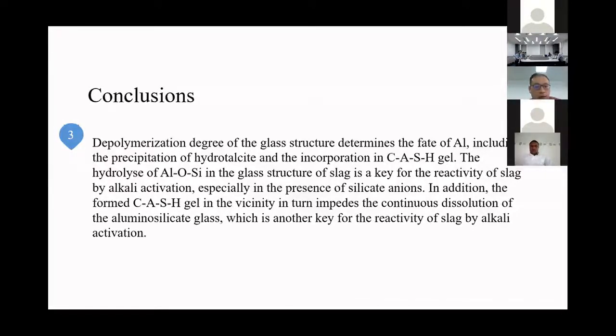But in the case of cement blends, the reactivity of slag is majorly controlled by the glass dissolution of the slag. Of course, the formation of C-S-H gel on the surface of the slag particles will also have an effect on its continuous dissolution, and this will be researched later.